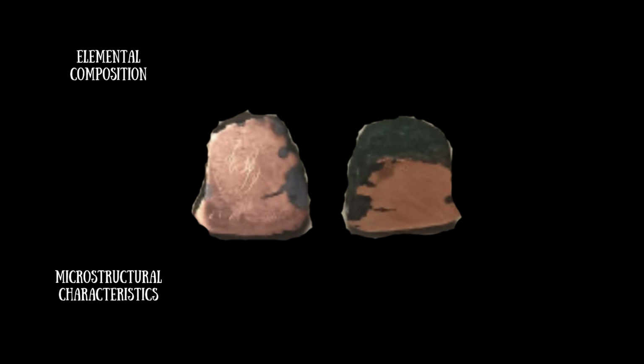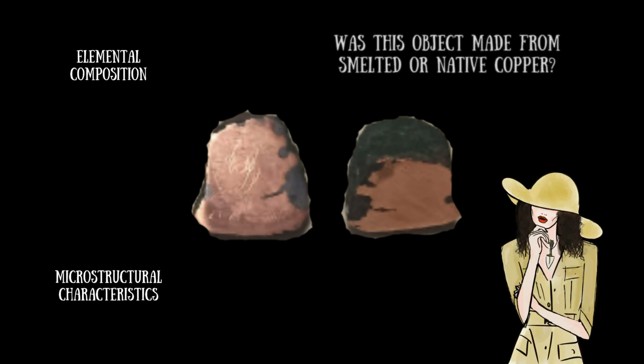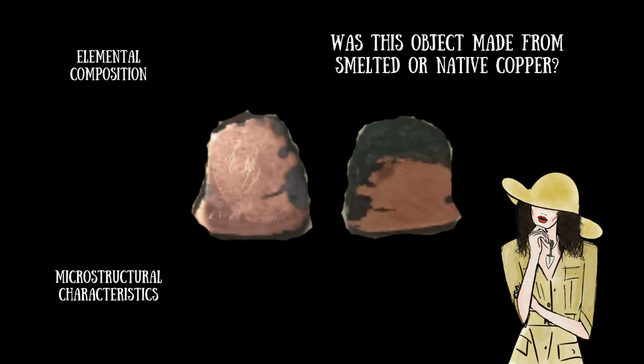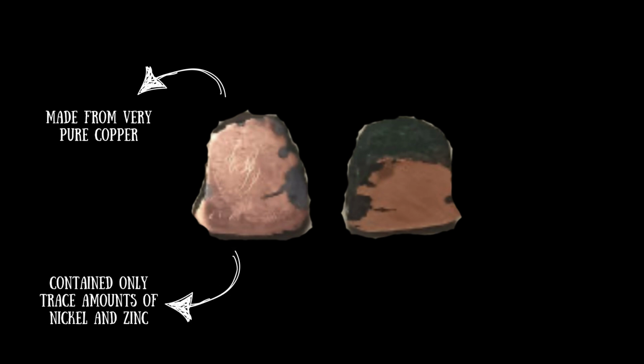As for the bar-shaped copper object, which may have been part of an unfinished chisel axe, they studied the elemental composition and microstructural characteristics of the artifact to determine, was this object made from native or smelted copper? The chemical analysis revealed that this object was made from very pure copper and that it contained only trace amounts of nickel and zinc.